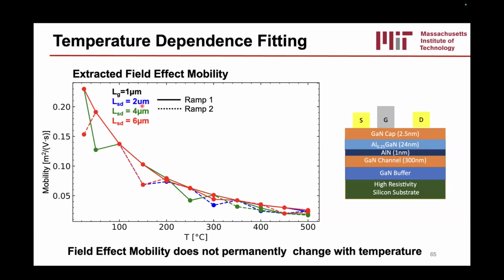And we can do one ramp in solid lines and then another ramp in dashed lines where we ramp the device up to 500 C, pull it back down, and then do another ramp here. You can kind of see the mobility values all lie on top of each other. So we see that there's really no degradation in the field effect mobility of the transistor as we go from one ramp to two ramp. And it's pretty consistent across several different device dimensions. So the field effect mobility, we can conclude, does not change permanently with temperature.